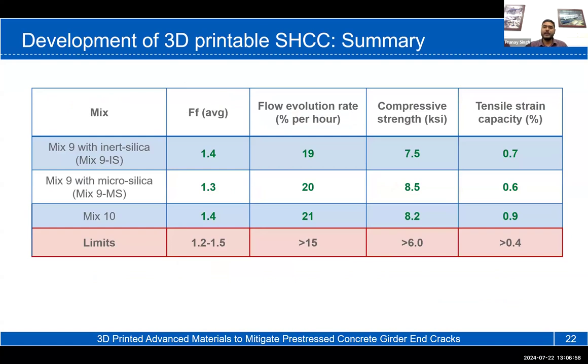In summary, for the hardened property testing and the flow criteria that we wanted to fulfill from the mix, all the 3 mixes have an average flowability factor, calculated from the drop table test we discussed in the previous workshop, in the range of 1.2 to 1.5, and that limit is what we found to be suitable for 3D printing purposes. The flow evolution rate should be greater than 15%, and our mixes fulfilled that criterion as well. The compressive strength and tensile strength criteria are also fulfilled by all the 3 mixes.